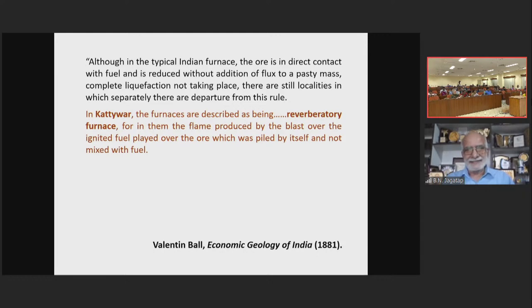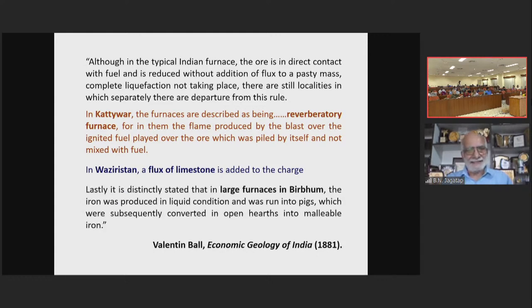In Kathiawar, the furnaces are described as being reverberatory furnaces, for in them, flame produced by the blast over the ignited fuel played over the ore, which was piled by itself and not mixed with the fuel. In Waziristan, a flux of limestone is added to the charge. And lastly, it is distinctly stated that in large furnaces in Birbhum, the iron was produced in liquid condition. So they had built furnaces which could withstand the temperature of the melting point of iron, and the iron was run into pigs, which were subsequently converted in open hearth into malleable iron.